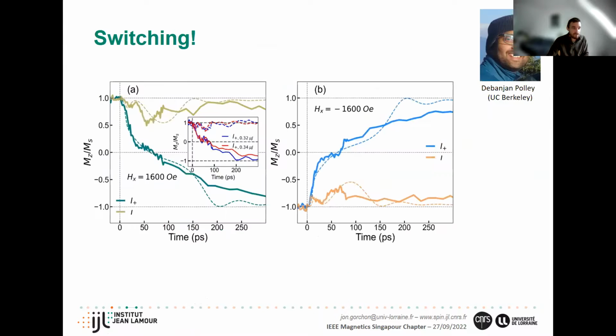So very quickly, I'll just let you know that very recently we got the data for the switching regime, which we struggled to get because the sample gets very hot. We have to use this focusing of the probe, and so it becomes really tricky to get the switching dynamics. So we got this in collaboration with Berkeley, who actually got this data.